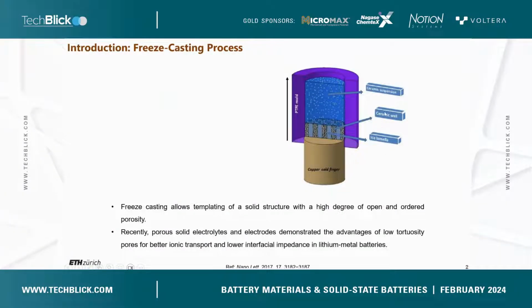shows you a schematic of how the freeze casting process is carried out. We have a PTFE mold, and this is placed on top of a cold copper finger. When we pour the ceramic suspension into this mold, due to the directional freezing of the ice crystals in the vertical direction, it would lead to the creation of this well-ordered structure. And once we remove the frozen ice through a sublimation process, we can create ordered porous scaffolds.